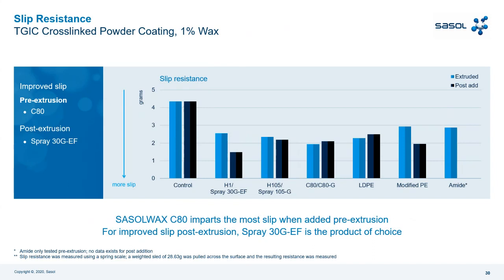Then we have the slip resistance. The test was done in pre-extrusion and in post-extrusion. In pre-extrusion, you can see the control that has a very high value, so less slip resistance. The best value is the lowest. You can see in pre-extrusion C80 imparts the best slip resistance, so C80 is in pastillized form. And then in post-extrusion, you can see Sasol Wax Spray 30 GEF, that is the ultra-fine micronized Fischer-Tropsch with melting point 100. Then, of course, follow the PE waxes and the LDPE waxes. In this case, Sasol Wax Spray 30 GEF in post-extrusion achieved the best results for all the tests, with respect to Sasol Wax and with respect to PE wax or LDPE or amide.